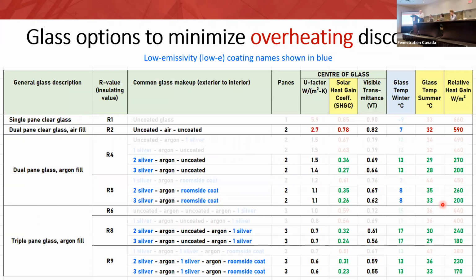So what are the glass options to minimize overheating discomfort? There they are. Choose double or triple silver products. And depending on what R value you need, depending what U factor you need, you might have a building code with a prescriptive value. And that prescriptive value might be 1.60 or 1.62 or something. And you might actually need an R5 product to get you that, or an R6 product. So you might be forced into having to use a product that has a lower U factor, and you might be forced into a room side coating that you would rather not have unless you spend more money and just get full triple glazing. But at least you know what your options are.